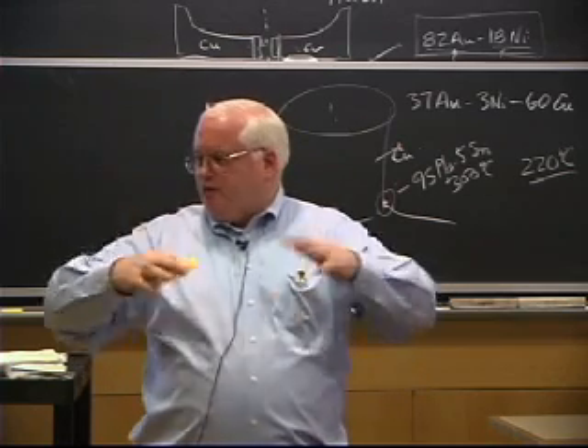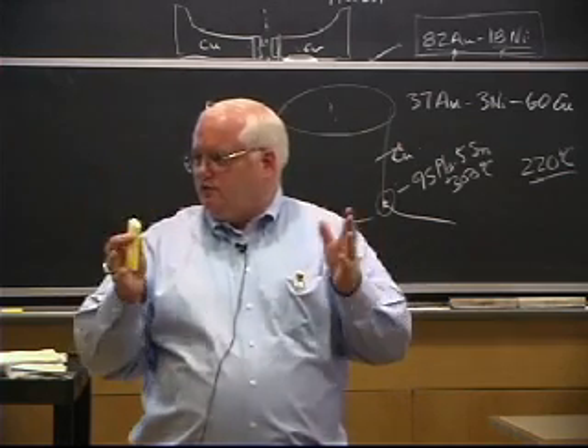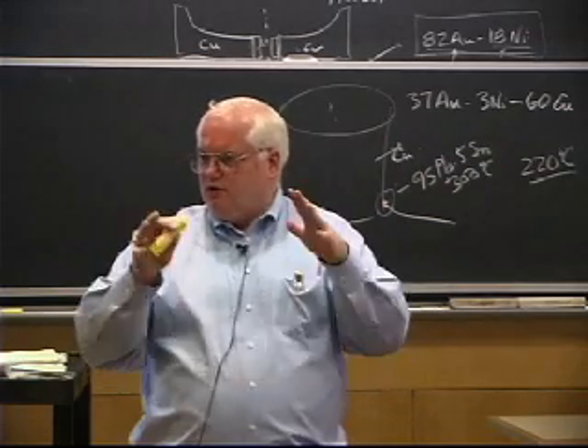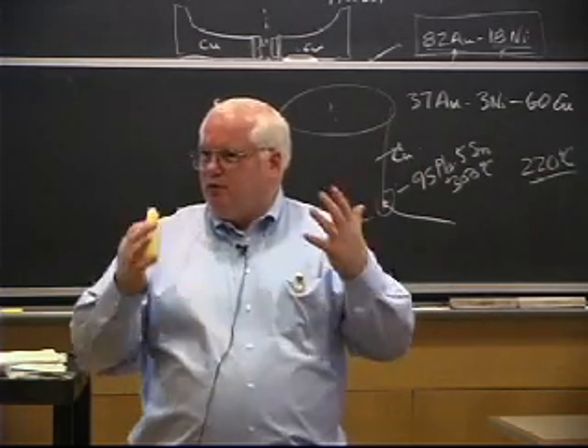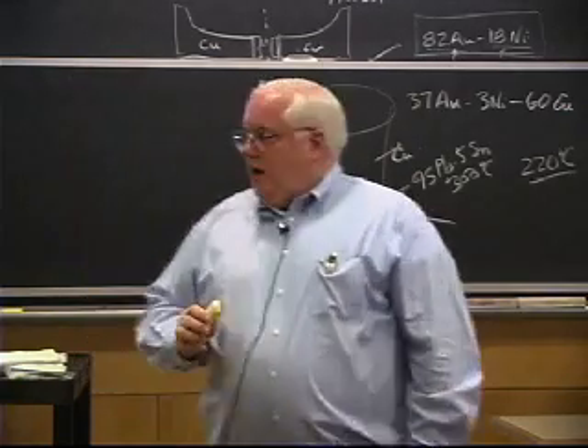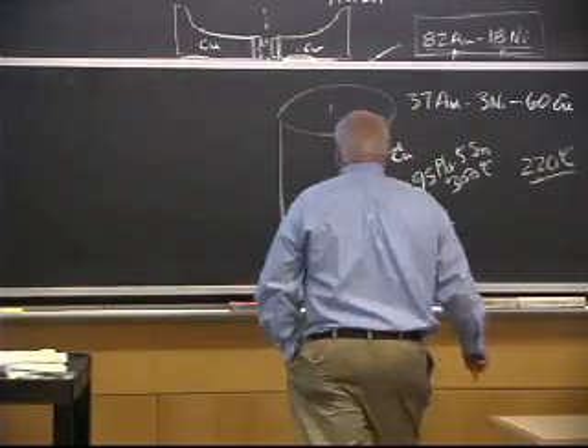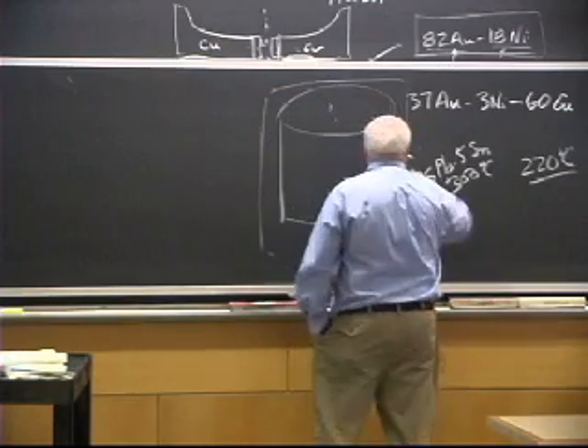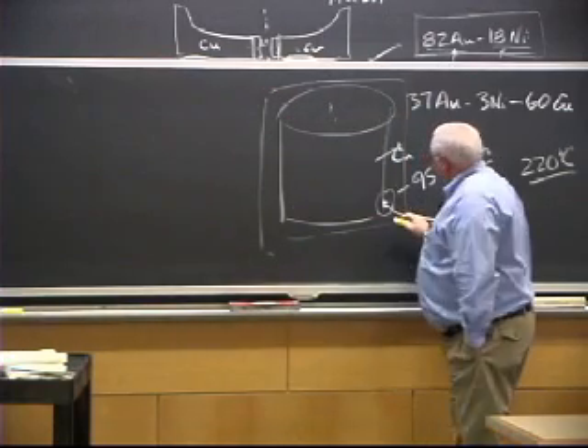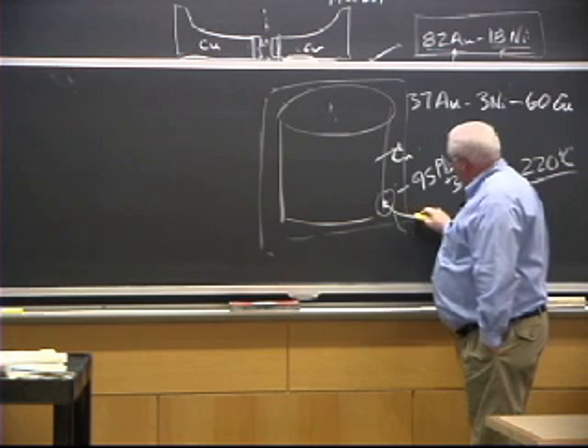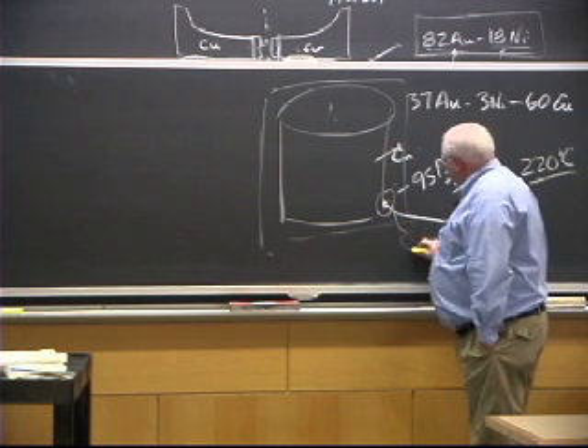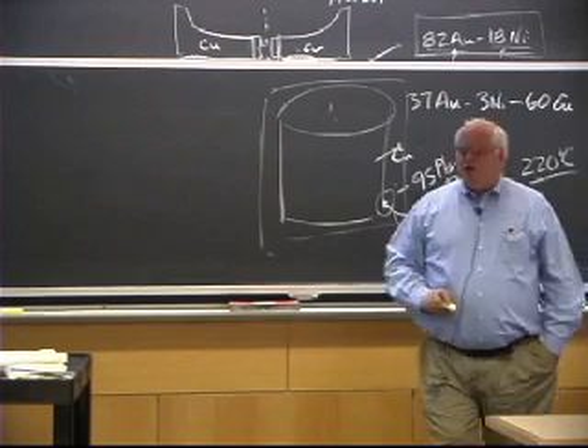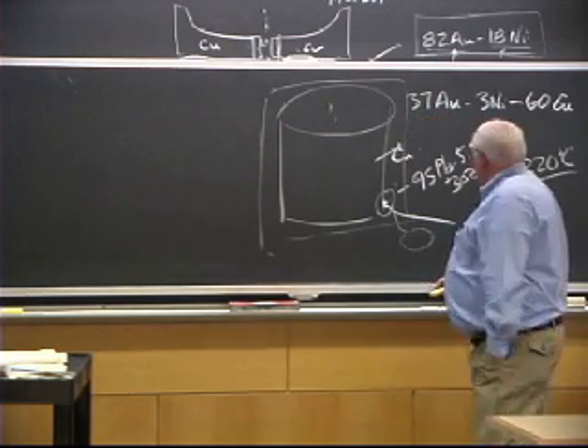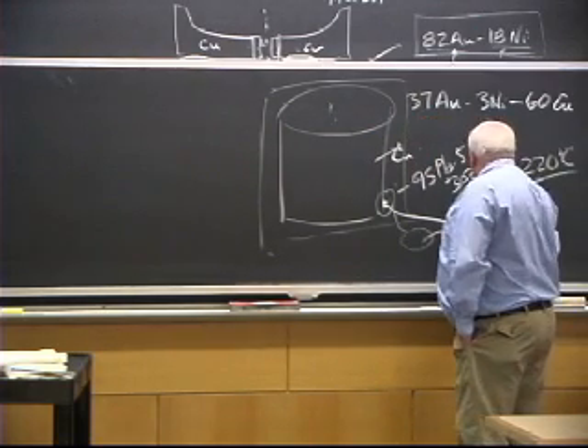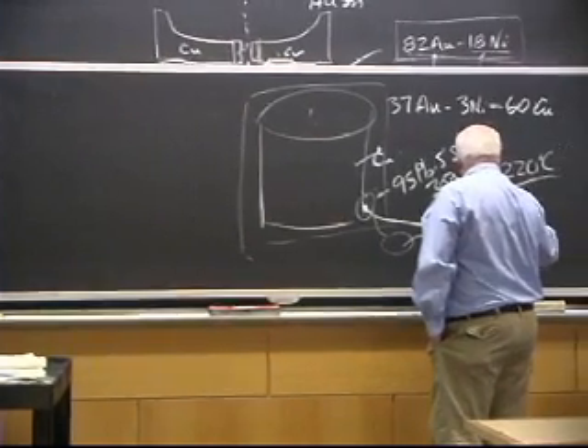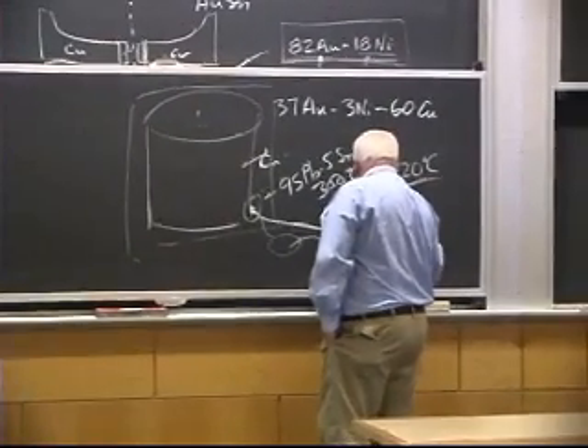And I guess the top of the reactor can get some high temperatures in bad situations, and so they didn't want to lose the ability to move the control rods, and so this thing had to be able to take certain excursions, right? Well, when they were doing the bake out, this whole thing is in some sort of metal container. It's a pretty good sized transformer. I actually never even saw them, but apparently there's a little hole where one of the leads comes through, and they got this little puddle of solder during the 220 degree test, and it turns out they analyzed it. It was 60 tin 40 lead, which happens to be the eutectic, which melts at 183.